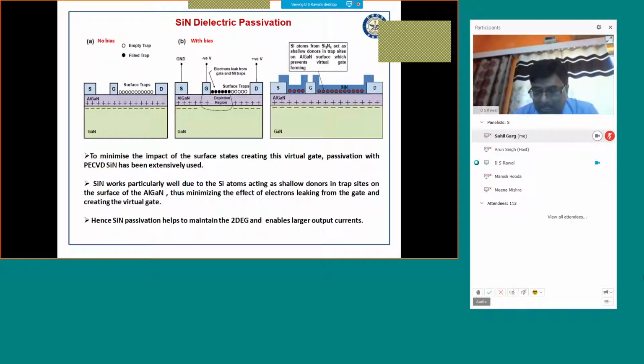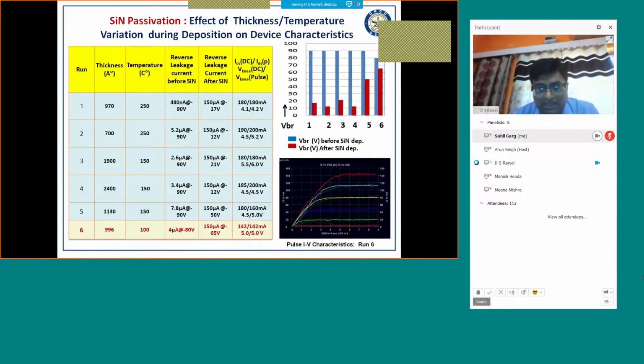So this is normally taken care of by the passivation process, and this is how we have optimized our passivation process. And this silicon nitride passivation is normally used in tensile strain, so that this tensile strain adds up in the piezoelectric polarization and increases the 2DEG to some extent, and therefore after passivation some increase in current and gm of the device is normally seen, but there is slight reduction in breakdown voltage also. So you have to optimize these parameters to have good current recovery or minimum current collapse with high breakdown voltage and good current density.